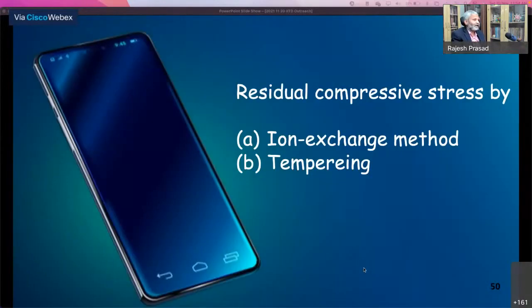One application I'll show you is your mobile phone screens. These are made of glass. Glass is extremely brittle and prone to fracture. So you make them fracture resistant. And how do you make them fracture resistant? Simply by putting in a lot of compressive stress. This stress is already built into the glass sheet by processes called ion exchange or tempering, and that's why it's called residual compressive stress. This is what makes your glass safer and less prone to fracture than if this compressive stress was not there.